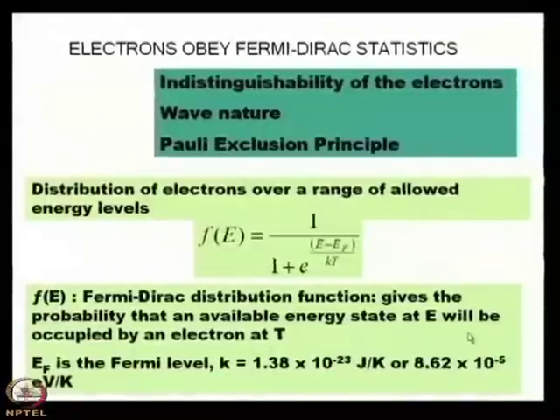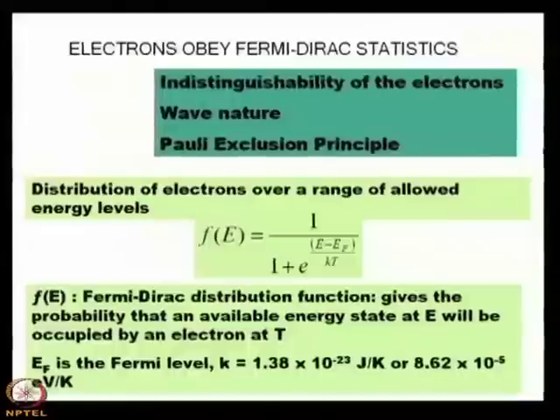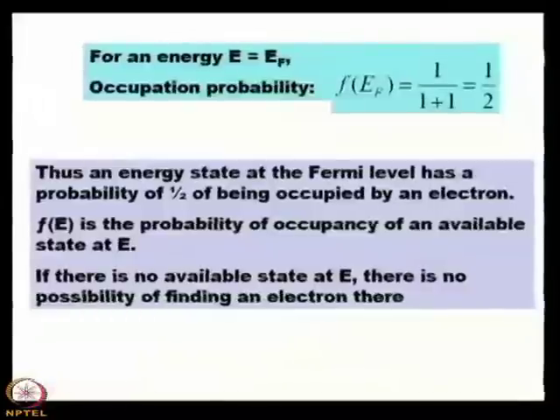Why are we interested in discussing the Fermi-Dirac distribution? It is because from the Fermi-Dirac distribution, you can calculate the electron or hole concentration in a semiconductor. For us, the number of electrons in the conduction band or the number of holes in the valence band is a very important parameter. When we design some material for a particular purpose — say you need 10¹⁷ electrons — you use the Fermi-Dirac distribution function to get the number of electrons or holes.